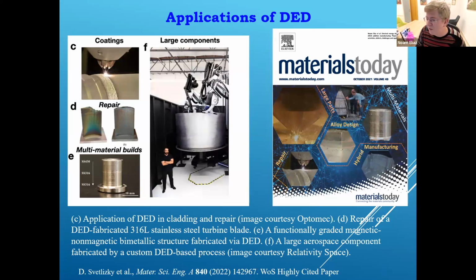So you can see the large size of parts that can be printed. In this case, a large aerospace component, but then you can also see the other applications. And in E, for instance, this is a functionally graded magnetic, non-magnetic bimetallic structure. Actually, I have with me an example of 420 stainless steel on one end, and Inconel 718 on the other end. And if I take a magnet, I can just travel and it will go from magnetic to non-magnetic. The reason that we kept this unpolished is just so that you can see the difference in the two materials according to the color. Otherwise, if I would polish them, you would not be able to notice.